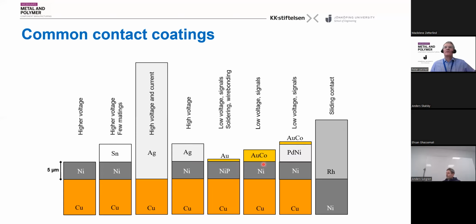And for normal switching contacts for electronics, low voltage, and for signals, you will have a stack where you have the copper layer in the bottom, nickel, and then hard gold on top. And the alternative to that is the one where you have nickel and a palladium alloy and maybe a flash gold on top, which could be hard gold or soft gold. And something we have not talked about is sliding contacts. If there are high demands on wear resistance and resistance to arcing, you could use rhodium as a precious metal of high hardness, but also very expensive.